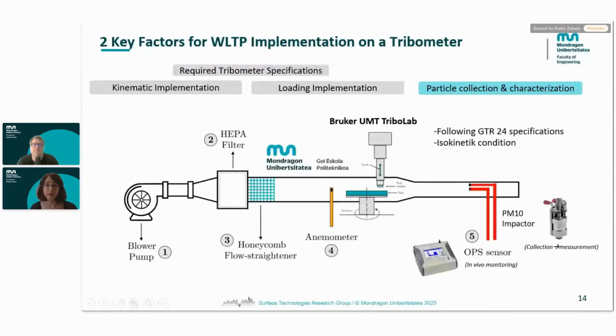Finally, we have the requirement for the particle collection and characterization. And here we can see the scheme of the setup that we developed in the Bruker UMT Tribolab following the GTR 24 specifications. First of all, we have the airflow and the air conditioning. Afterwards, we have an anemometer in order to measure the speed of the air and to adjust it so that we can ensure isokinetic conditions. And finally, we have 2 sensors for the emission characterization. On the one hand, we have an optical sensor for in vivo monitoring of the emission. And on the other hand, we have an impactor to physically collect all of the particles so that we can measure the weight later on.